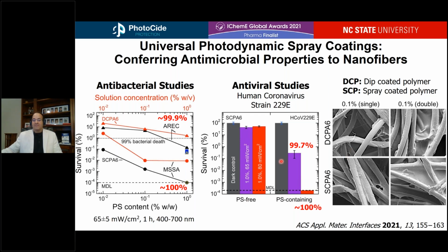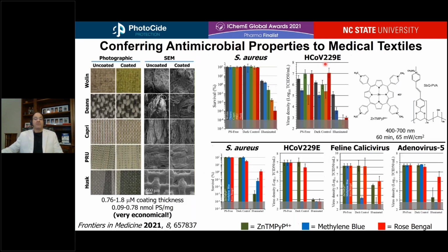However, in the presence of our photosensitizer embedded within the coating, we're able to inactivate coronavirus depending on the intensity of the visible light that's being used. Anywhere from 99.7 to essentially our minimum detection limit, 100% inactivation. And again, this is conferring the antimicrobial properties through the use of our universal photodynamic spray coating to nanofibers. However, we can also do that to medical textiles and upholsteries.